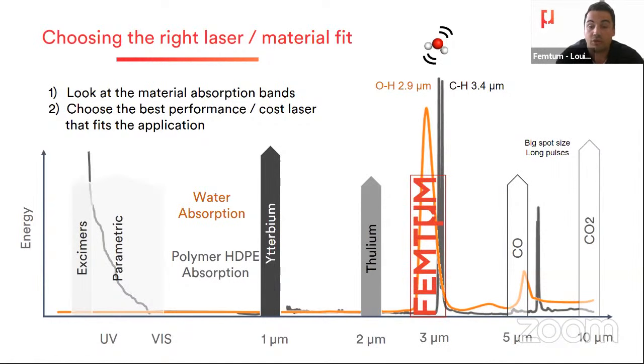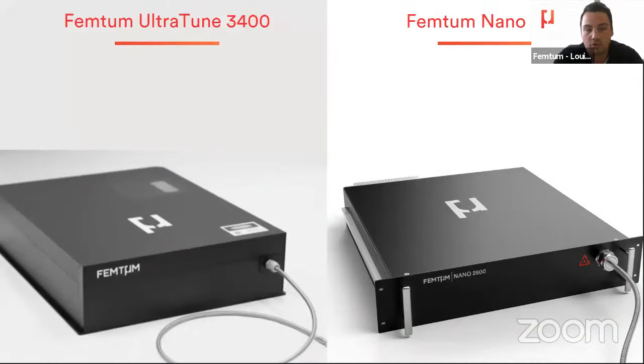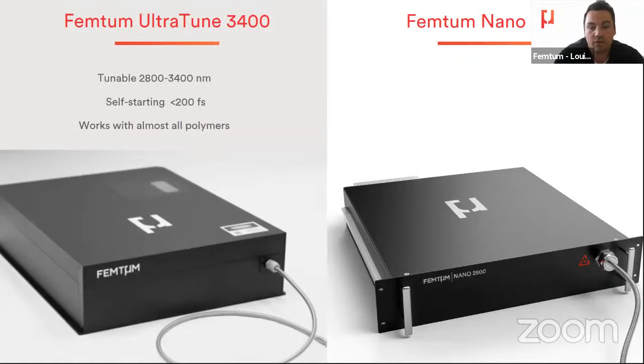Femtum, we bring the first generation of short pulse fiber laser emitting directly on those resonances. We have two products right now, the Femtum Ultra Tune 3400 and the Femtum Nano 2800. The first one, it's a tunable femtosecond fiber laser between 2.8 and 3.4 micron. It's done very easily via software, it's done electronically.